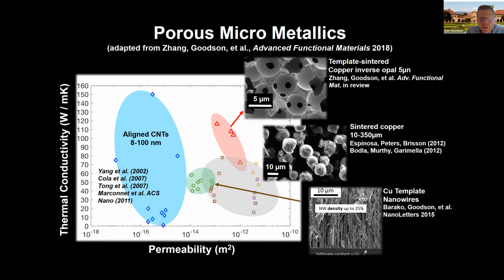So one of the exciting things that you can do is then look at classical sintered copper, which is here, and this is the permeability for fluid flow in classic sintered copper, and then you have thermal conductivity as a function of the permeability. Here I'm showing you can get very high thermal conductivity using, for example, carbon nanotubes or other devices, and the permeability remains a little bit low because they're kind of densely packed. On the other hand, if you are able to do this template-sintered copper, you have the chance to make both a high permeability and a high thermal conductivity at the same time. So it's not diamond high. Diamond is 1 or 2,000, but it's pretty high compared to a porous medium, and the fluid permeability is high